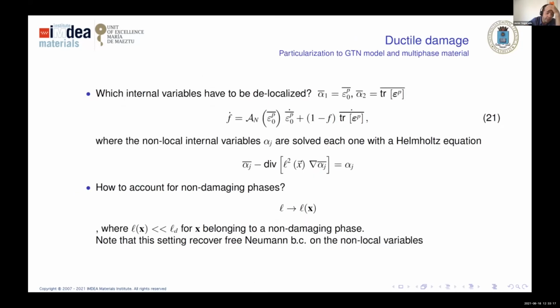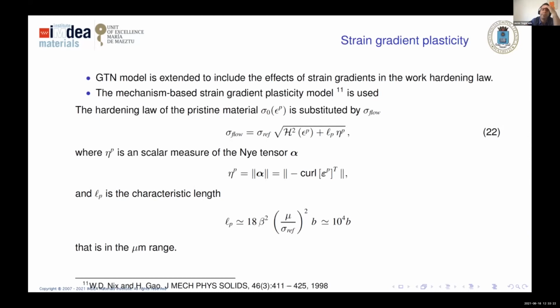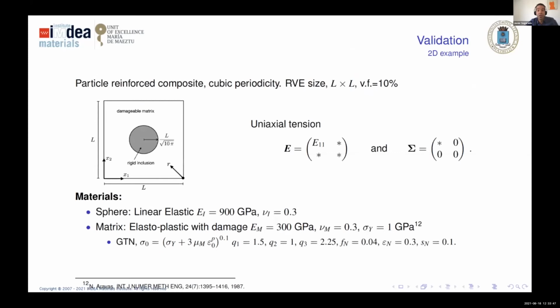So we have the first part that is the gradient damage model, and the other is strain gradient plasticity. What we're using is the mechanism-based strain gradient plasticity model that is exactly the same as the crystal plasticity counterpart. It's based on the Nye tensor through the curl of epsilon p, and it introduces an expression that emulates Taylor's. Let's say that it is the upscaling of the previous constitutive model. So we're now going to see how it works on particle reinforced composites, first in 2D.